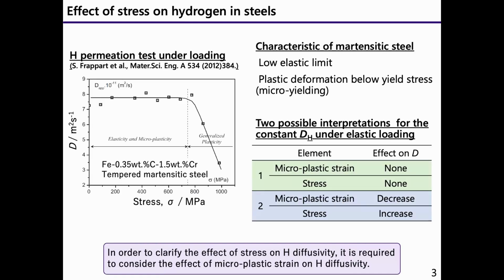However, martensitic steel has low elastic limit. It means plastic deformation occurs below yield stress. It is called micro yielding. In that case, there are two possible interpretations for the constant diffusivity under elastic loading. The first interpretation is that both microplastic strain and stress have no effect on diffusivity, so hydrogen diffusivity is constant under elastic loading.